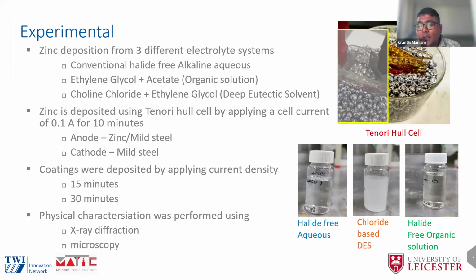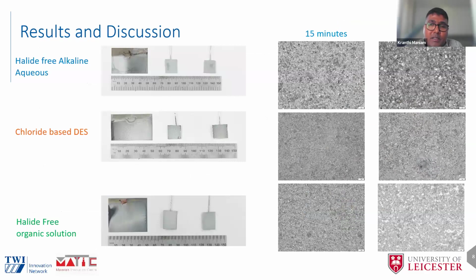And you can see on the right, you have three different solutions. One is the halide-free aqueous, which is transparent and aqueous based. The chloride-based deep eutectic solvent is a bit turbid, whereas the organic solution is clear. This is an optical microscopic image on the right, which shows that there is a coverage of the deposition, whereas the top left image shows the Tenori Hull cell panels with full coverage, and the two square pieces on the right show the depositions at two different timings by applying a particular current density.